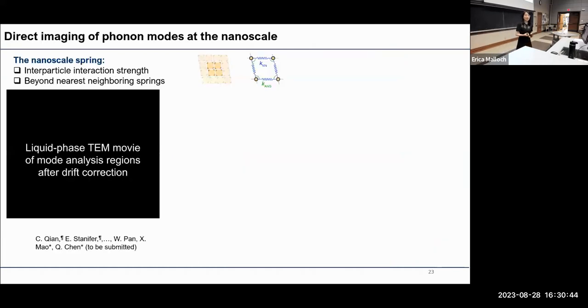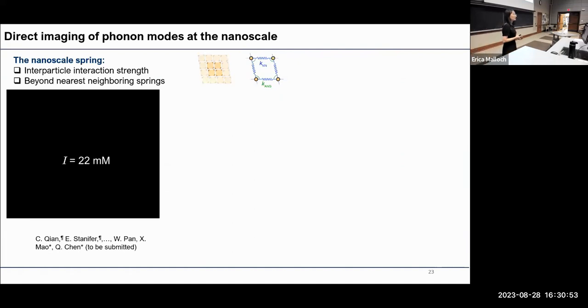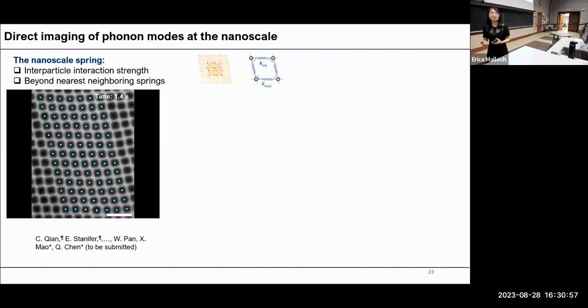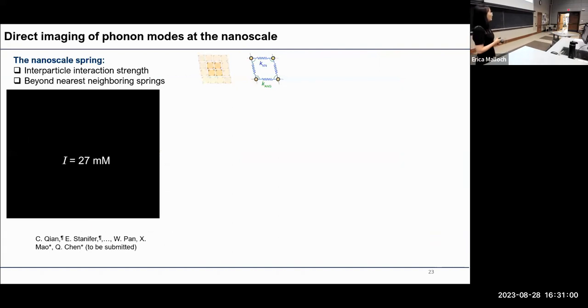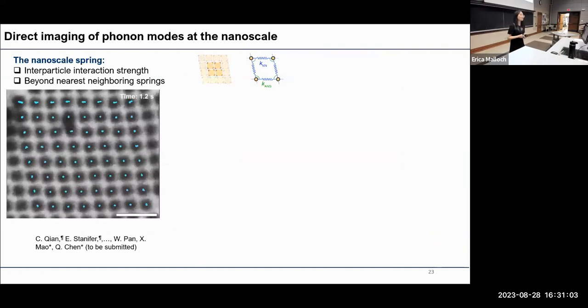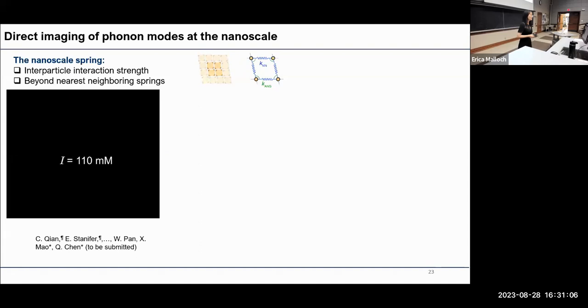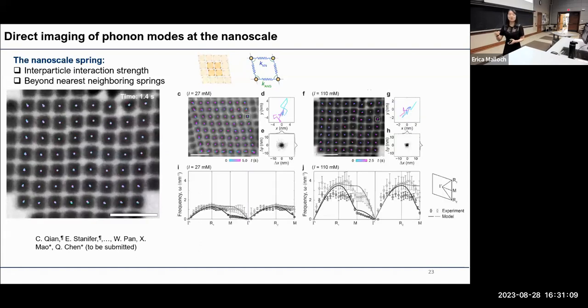The soft modes, together with the nanoscale springs, which determine the soft modes, can actually both be measured using liquid phase TEM. So here I'm showing a series of liquid phase TEM movies of 3 different Maxwell lattices under different conditions. Here we can do single particle tracking, following the position of each single particle. We can do global drift correction so that in the end, what we can look at is really just the local vibrations of particles at the lattice sites. And then we can derive the really amazing phonon dispersion spectrum as shown here. The phonon dispersion spectrum has an x-axis, which is the position in the first Brillouin zone, and the y-axis is frequency or energy scale.